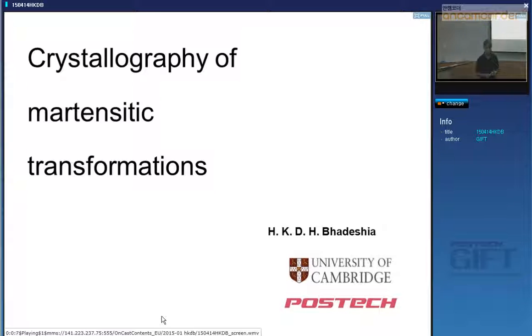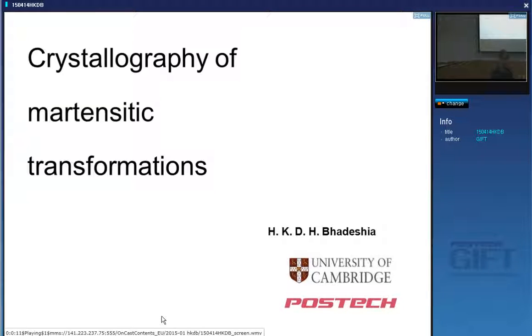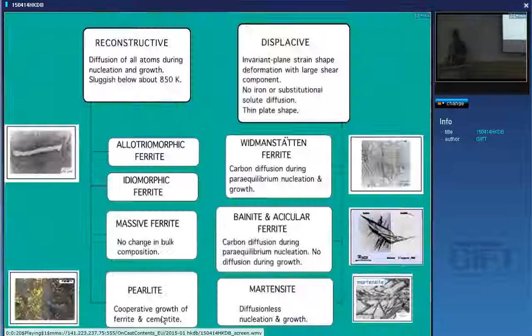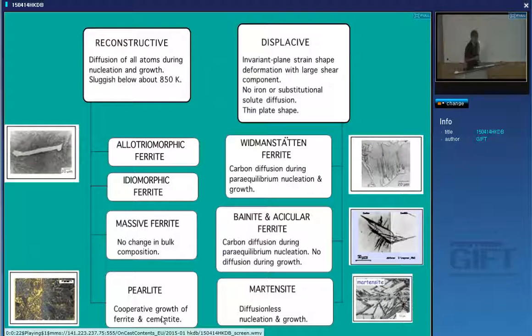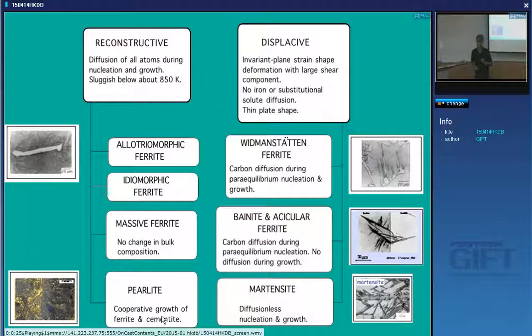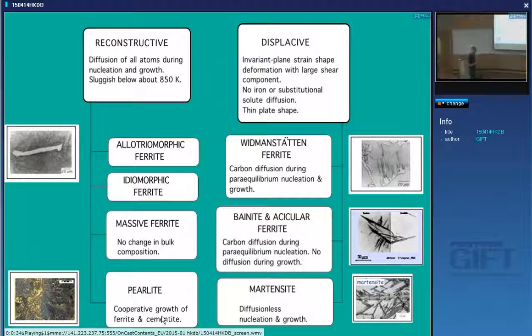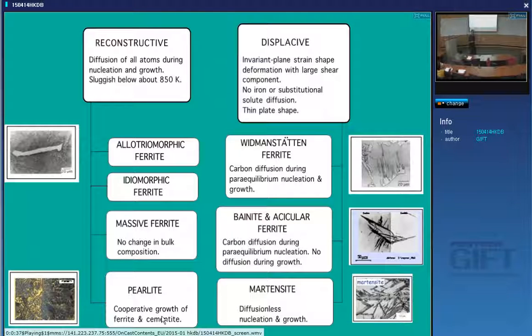Today I'm going to start by introducing the characteristics of martensite so that we can deal with the crystallography of the transformation from austenite to martensite. Before I go on to martensite, these are the major transformations that happen in steels and you can divide them into two parts. These are called reconstructive transformations — you take the unit cell, break all the bonds apart and arrange it into another pattern, allowing diffusion to happen so the strain energy is minimized.